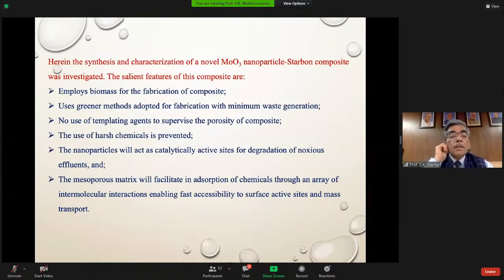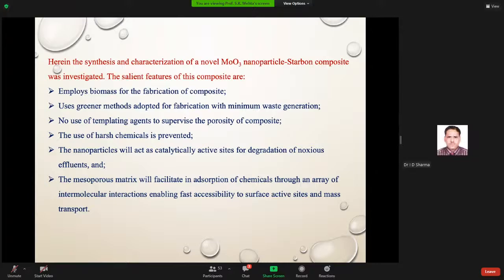So my student did the synthesis and characterization of novel molybdenum oxide nanoparticles, Starbon composite. And basically the salient features of these composites are: it employs biomass for fabrication of composites, uses greener methods adopted for fabrication with minimum waste generation, no use of templating agents to supervise the porosity of the composites, and the use of harsh chemicals is prevented. The nanoparticles will act as catalytically active sites for degradation of noxious effluents. The mesoporous matrix will facilitate adsorption of chemicals through an array of intermolecular interactions, enabling fast accessibility to surface active sites and mass transport. So these are the salient features.